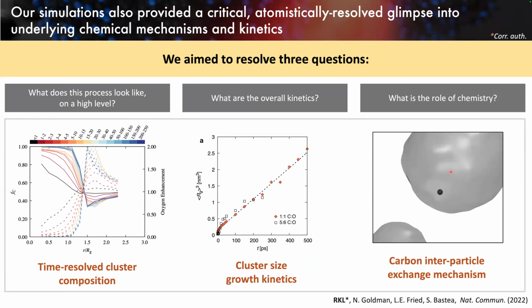This is important because when we look at the slope of this Ostwald ripening curve, the slope is going to be dictated by the kinetics of that chemistry. So one of the ways we can potentially control the size of the particles we get would be by modifying the chemistry happening in this solution. That would go back to saying, maybe we want to adjust the composition of our precursor so we can control that chemistry. Again, interesting insights that hint at ways we might control this process.